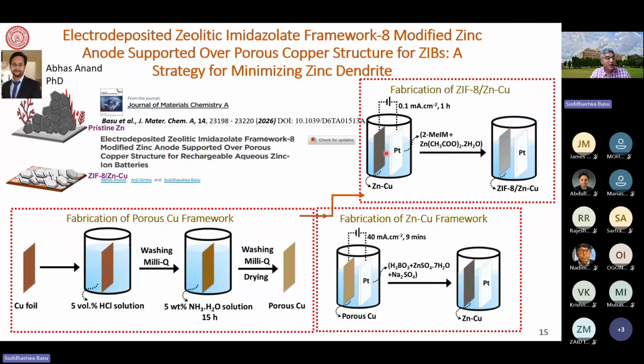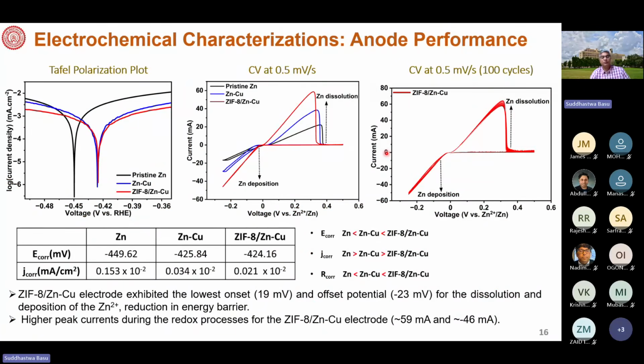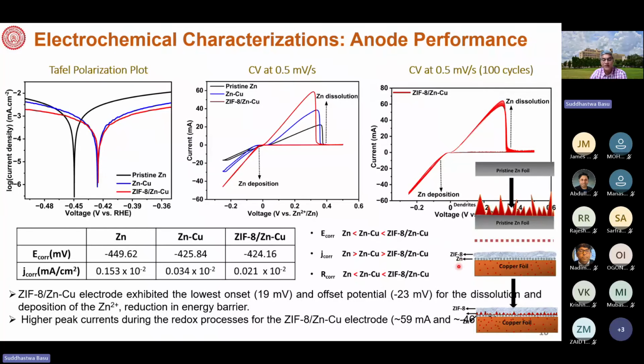I'll show you schematically how this is possible. If I do not have that ZIF8 structure, then the growth of dendrite takes place, sharp peaks, and they're very strong. As I said, the 100 gigapascal is the Young modulus of these zinc dendrites. And if I have a copper foil with a ZIF8 layer on it, then the growth is not so apparent as shown here, and there is nowhere to go, so they don't really increase in the peak size that we have shown you here, but they go a little bit in the lateral direction on the left hand side and right hand side for the growth. So that is what is captured.